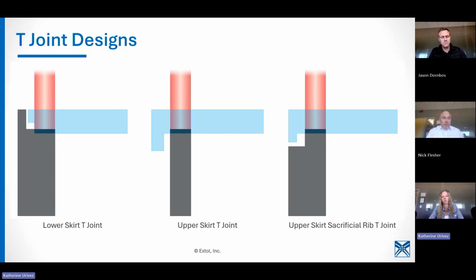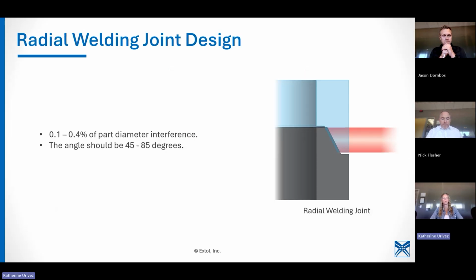Lower skirt T-joint, we see this quite often for highly aesthetic applications. I'm thinking in terms of lighting applications, we'll see that. Upper skirt T-joint, that's for when you need to locate a lid or have high automation. If you're running seven figures of parts, like millions of parts, that's something to think about. Radial weld joint designs. You could do this by rotating the part. We find it's more cost effective really to still use a galvo and use a mirror, and you can bounce the laser around and come in perpendicular to the part.